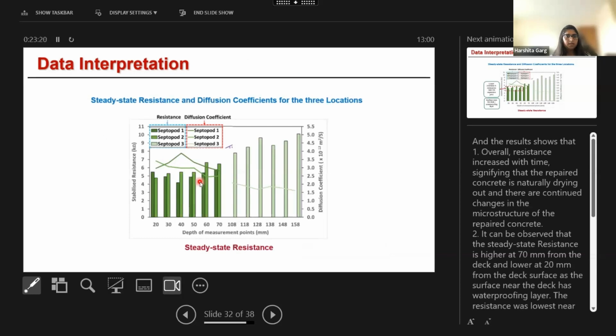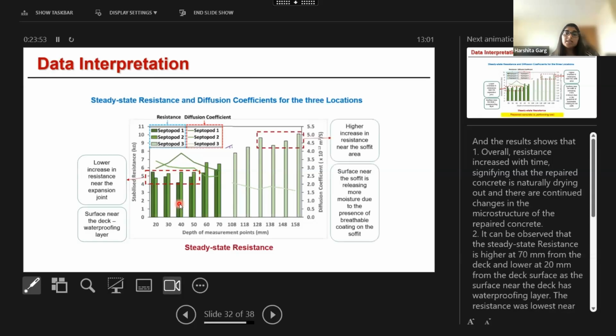So overall, we can see that resistance is increasing with time, signifying that the repaired concrete is naturally drying out and there are continued changes in the microstructure of the concrete. Secondly, we can see that resistance is lower near septopod 1 and 2. It is lower near the expansion joint because the surface layer near the deck has a waterproofing layer. Resistance is higher near the soffit, again because of the breathable coating on the soffit, which is releasing more moisture. But overall, the repaired concrete can be seen performing well.